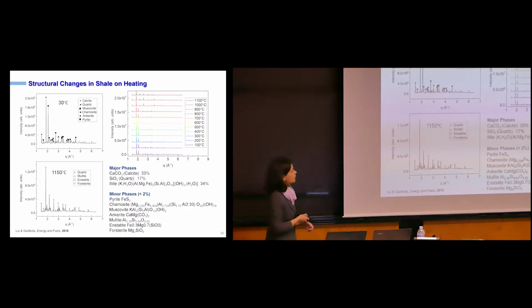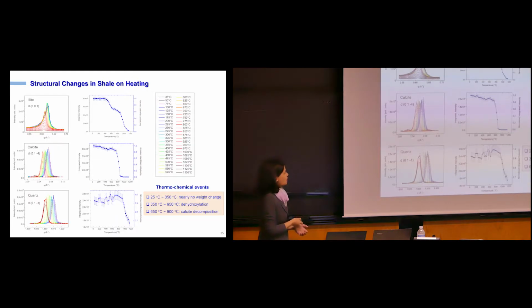So we used ultra small angle, wide angle X-ray scattering measurements, looked at what is happening to shale as an example, found out, again, this is basically heterogeneous material, has a mixture of a lot of different materials. But what is interesting is that when we go up to high temperatures, it starts to behave like a sintered solid, right? So for those of you who work in the area of ceramics, what we find is that this layered clay that is present starts to lose its layering. Calcium carbonate that's present loses its CO2. Quartz changes its structure.